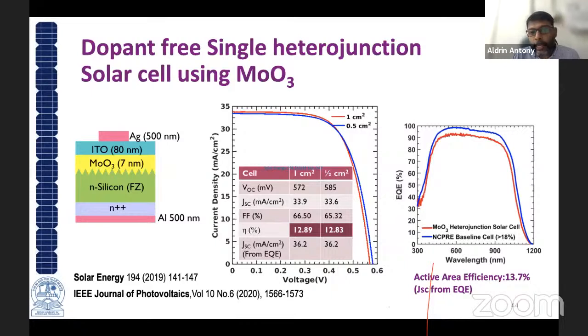And this is the first solar cell we made with MoO3 on one side. Over the top we put an ITO as a contact layer, and then silver grids over the top. On the back side, we put an N+ layer by thermal diffusion. This forms a single heterojunction solar cell. This is a dopant-free metal oxide, moly oxide, on one side. The efficiency we got was around 13%, and this is a very good IV curve for the 1 centimeter square area solar cells.